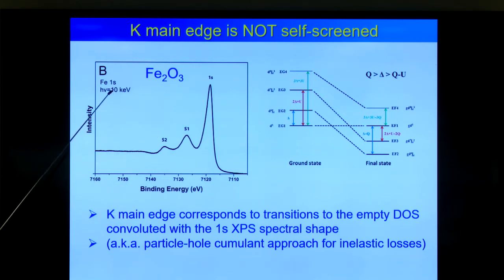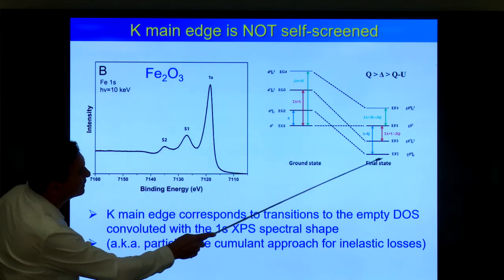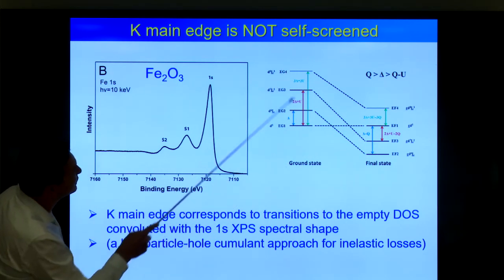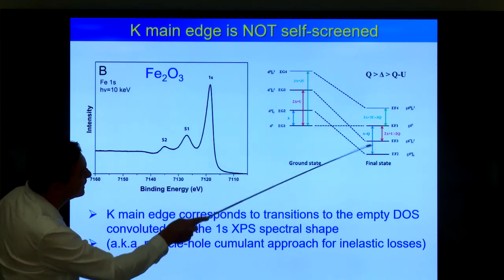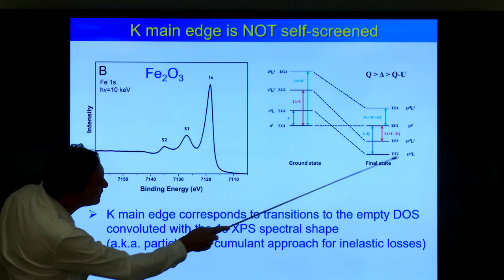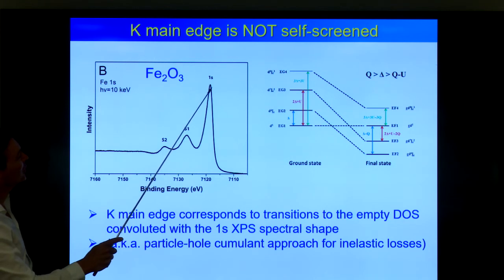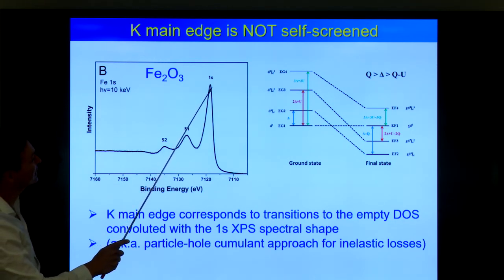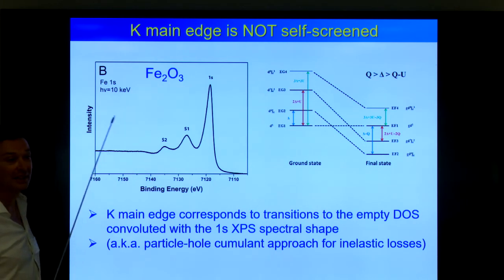This is a 1s photoemission on iron oxide, and then you see directly the different screening processes. So this is the well-screened peak, and then you have satellite 1 and satellite 2, and they come from all the different screening channels. So the mostly screened peak. So now I do four different configurations, d5, 6, 7, and 8 with ligand holes, and then in the final state I do all the energetics, and then the well-screened peak is core hole d6 ligand hole. So that's this one. So that's where you do your normal fully screened DFT calculation. But then you miss these two satellites.